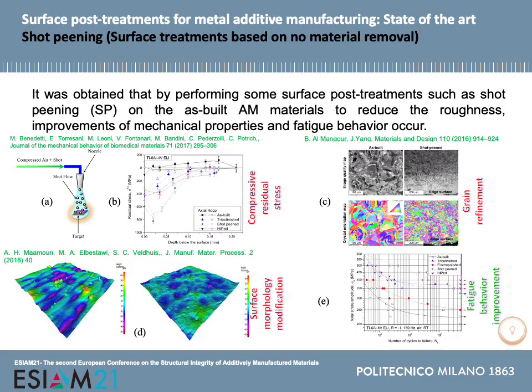Shot peening is a mechanical surface treatment and cold working process which is used small impacting media bombarding the target, as you can see schematically here. By applying shot peening, compressive residual stresses in high range are induced in the surface of the material. In addition, surface of the as-built state can be modified in a good way. Also, by applying shot peening, considerable grain refinement in the surface layer can be obtained. These 3 factors and effects of shot peening resulted in fatigue behavior improvement of the material, as you can see in these studies.